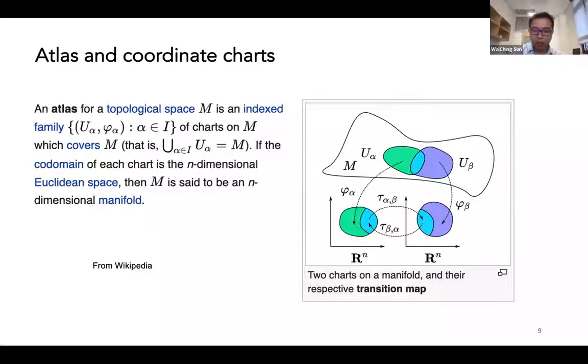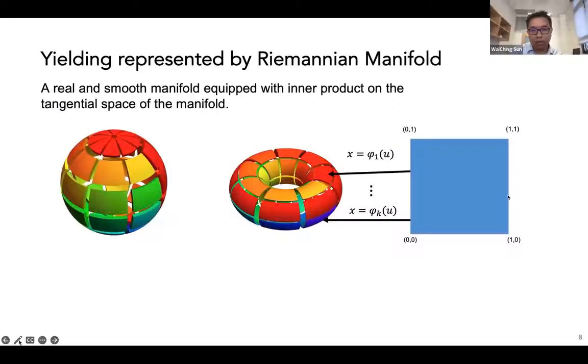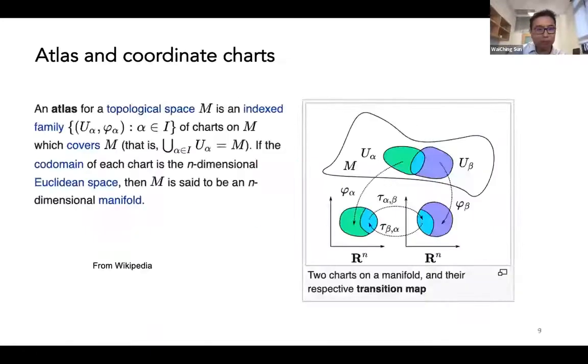Basically, in this case, what the machine learning did is actually to learn a mapping. If you worked on finite element before, you probably will recall isoparametric mapping. Here, the thing is not exactly identical, but you can say we get the inspiration from it: we want to have some measurements in which the material initially yields, and what we want to do is to create those patches and then try to deform them in the stress space in the possible way so that they are matching all the point cloud that we obtain from the stress measurement that detects the yielding.